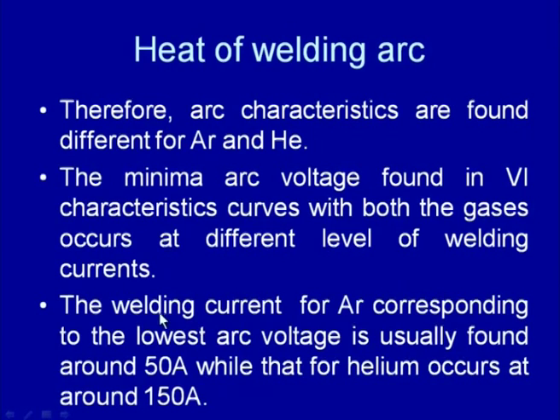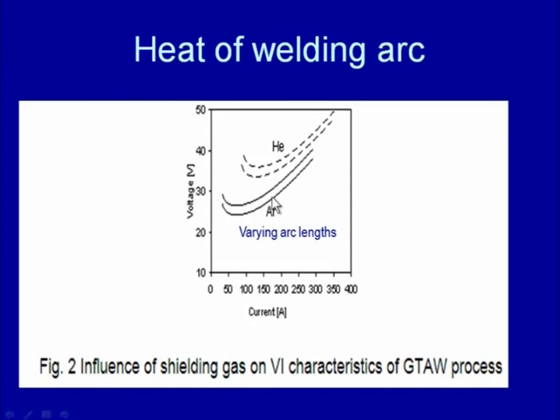So, the welding current for argon corresponding to the lowest arc voltage is usually found around 50 ampere, while that for helium it occurs around 150 ampere. This is what we can see in this diagram also. If you use two different arc lengths, then for a given shielding gas two different VI characteristics are obtained, but if we change the shielding gas, then for identical arc lengths there will be a huge change in the VI characteristic curve location.